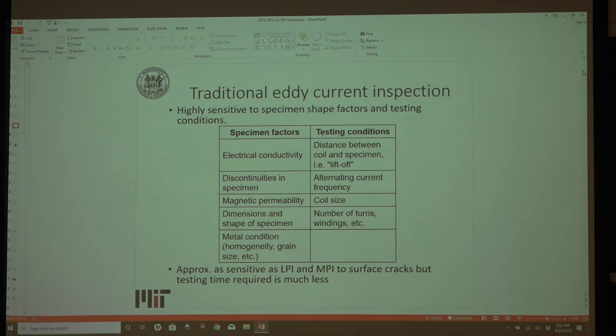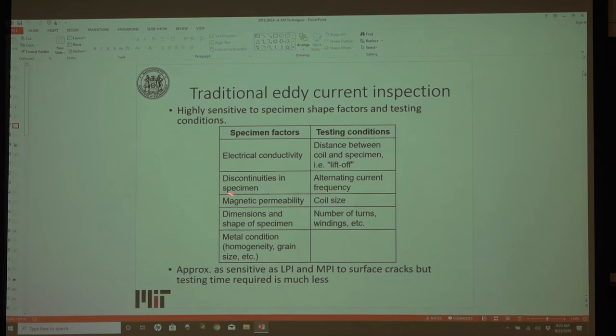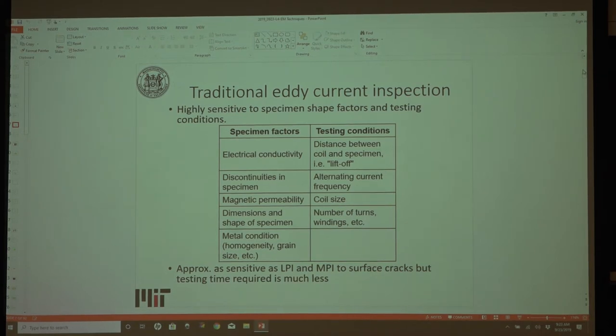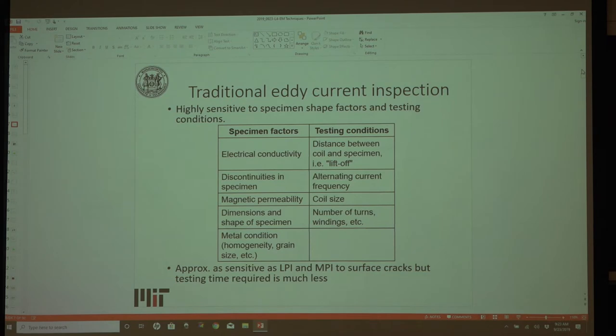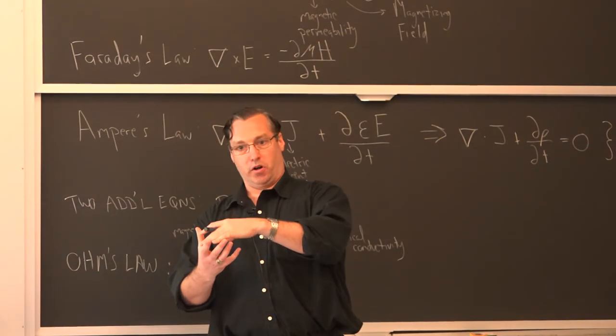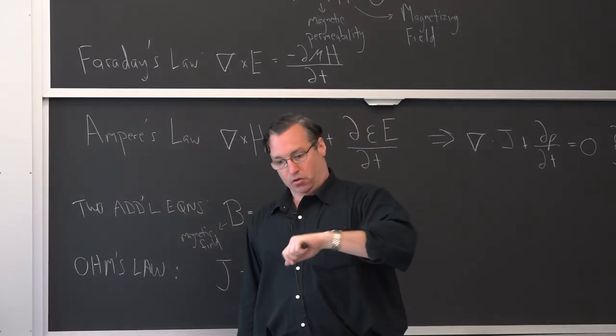You need to understand the testing conditions before doing the inspection so you're not making a go/no-go call without all the information. Specimen factors taken into account include electrical conductivity, which ties into liftoff distance. If you have an aerospace component with a leading or trailing edge that has taper or geometrical curvature, liftoff can be an extremely critical variable. In the real world you don't have homogeneous flat-plate samples — they have tortuous geometries, internal pores or cooling channels — so you need to understand the liftoff as you're going over that geometry.